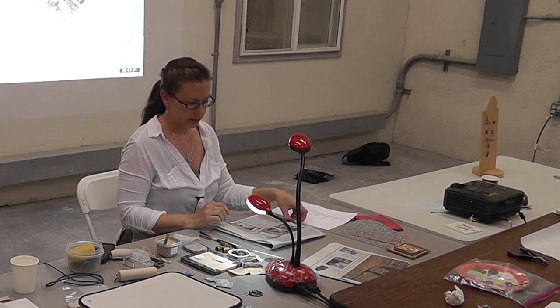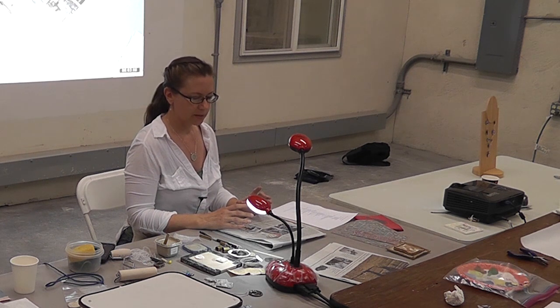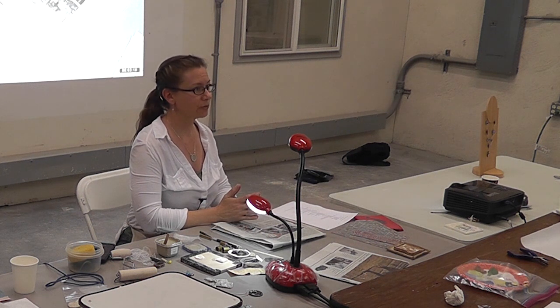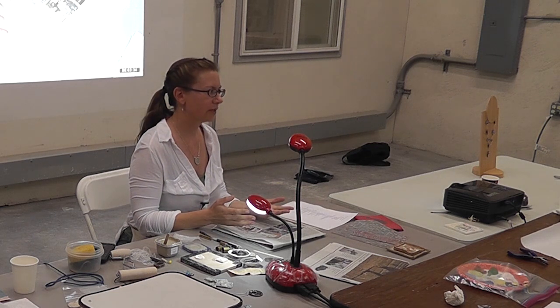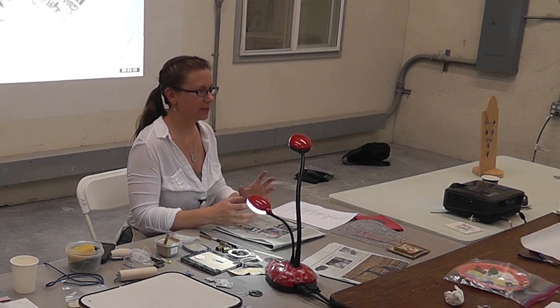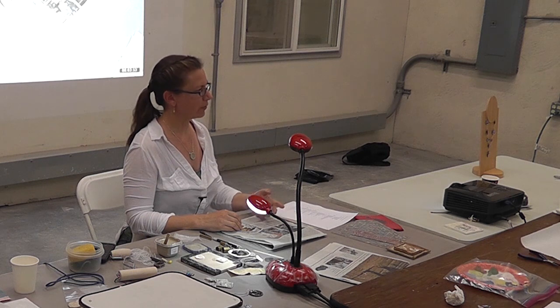I like to work on newspaper and roll out my clay in small slabs. I never use the slab roller because it's going to dry out quickly. I work with porcelain primarily — you can use any clay you want. I choose porcelain because I like the white, because the colors pop, and because porcelain accepts a lot of fine detail. Higher Fire is a cone 10 studio, so everything I do is cone 10. I also like the glazes in reduction at high fire because of the depth — there are jewel-like tones that come out.